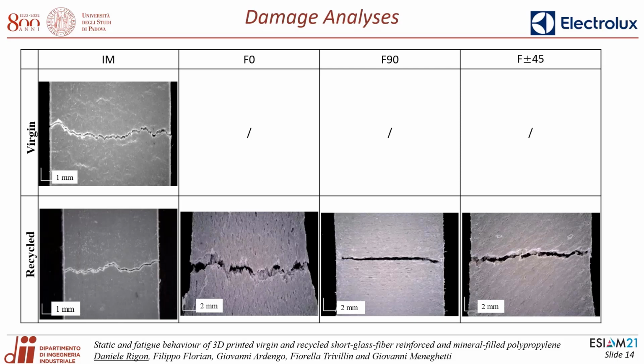Looking at the macroscopic damage mechanisms, as reported in the first column of the table, injection molded virgin and recycled specimens exhibit the same macroscopic failure modes observed in static failure, with fracture surfaces almost perpendicular to the load direction. In the case of recycled F0 specimens, the failures initiated at the start point of the fillet due to the presence of defects generated by the previously illustrated peculiar infill strategies, and then propagated in a zigzag appearance. In the case of recycled F90 samples, the fracture surface is planar, normal to the loading direction, located at the interface between adjacent filaments. Finally, the macroscopic fracture surface is almost perpendicular to the load direction, as observed in static failures, as shown in the last column.